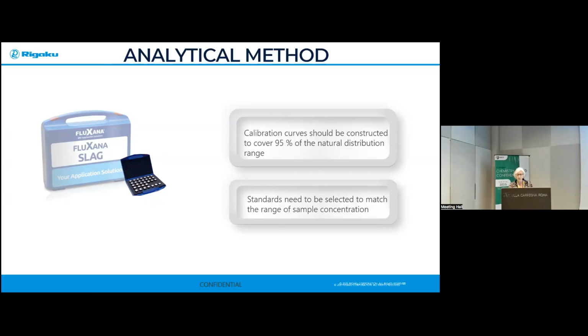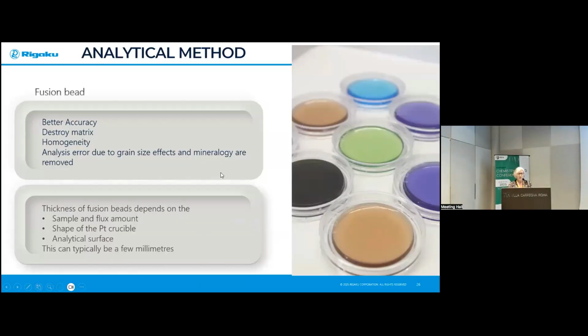The standards that we use need to have the correct concentration, otherwise we will not have an accurate and precise determination. So, as I mentioned, the fusion is the best for accuracy. We take away the error from particle size and matrix. We get a very homogeneous mixture, and we ensure that the thickness of the fused bead depends on the sample and flux amount, and the shape of the analytical mold will determine the analytical surface that we will measure. So here you can see an example of some fused beads, which are glass matrix.